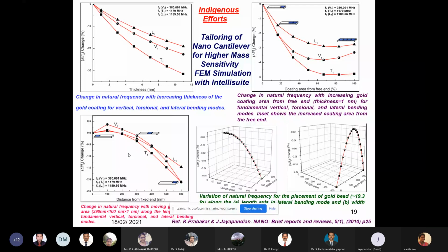Here, the right-hand side bottom is actually the lengthwise as well as the widthwise. We are adding a gold bead of 19.35 femtogram. These are all simulation results only. Then we are able to get an interesting result at 200 nanometer, a fantastic change in resonant frequency, a zeptogram mass measurement. We are able to get it.